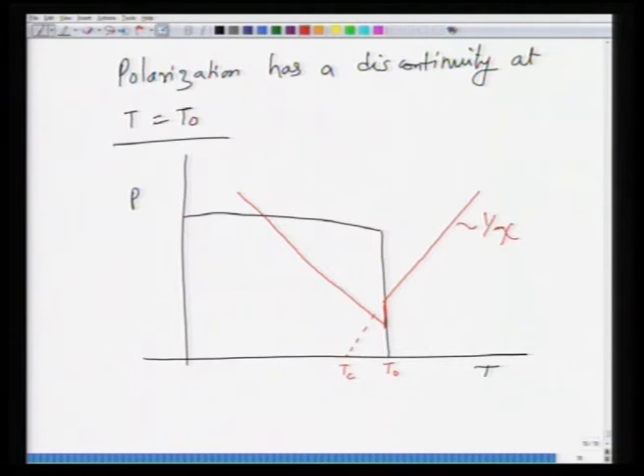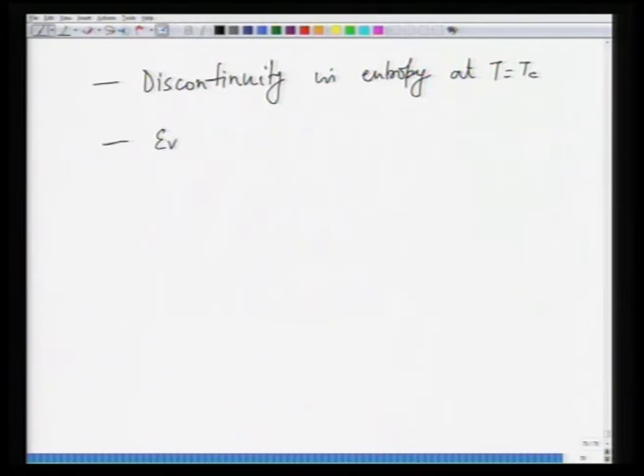So this is 1 over chi. In addition, not only do you have entropy which is discontinuous, but since there is a discontinuity at T equal to Tc, you also have discontinuity in entropy at T equal to Tc, and you also have evolution of latent heat. So for the first order transition, these are two important features that make it different from the second order transition.